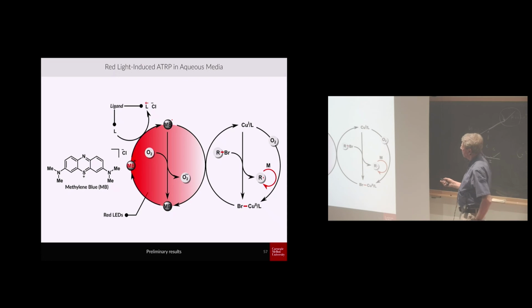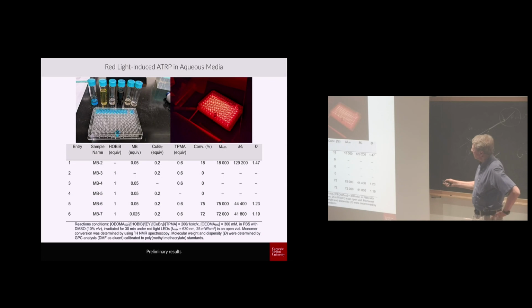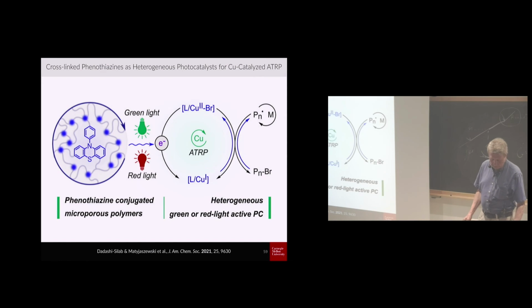Another example is methylene blue. So it is also a dye, which would be organic. And in that case, it can have a redox potential in a range of -1 volt. So it can reduce copper to copper 1 and start the polymerization in a proper way. So this is 96 well plates, and you can irradiate with this blue light, or in that case, red light, with good control of molar masses and dispersities.